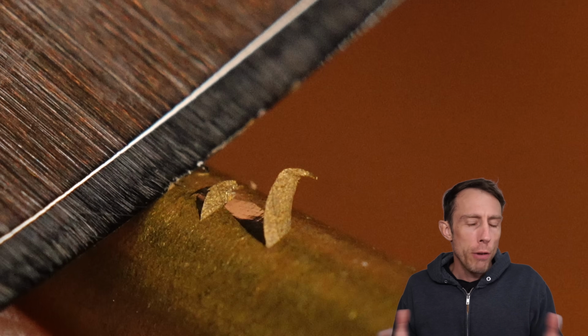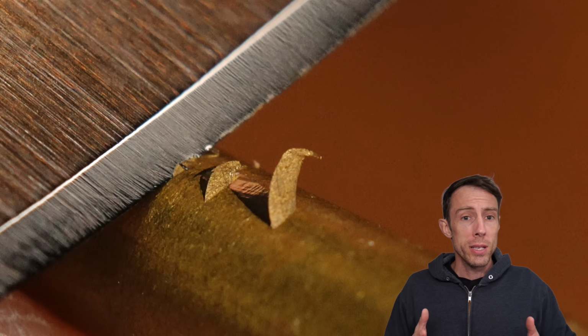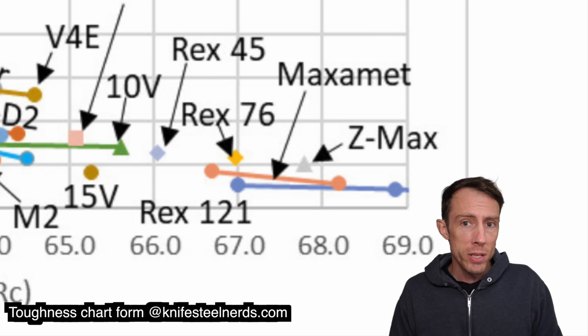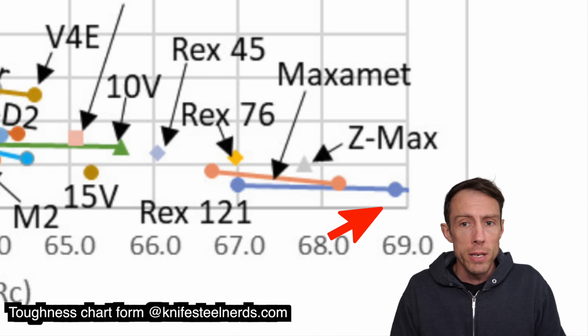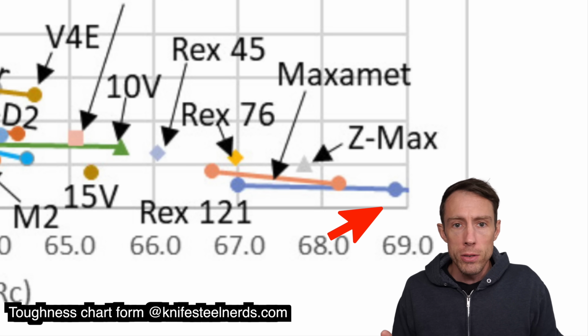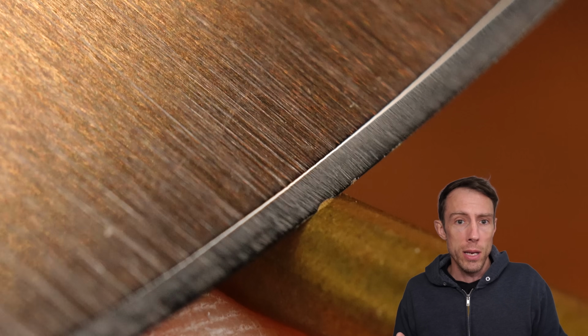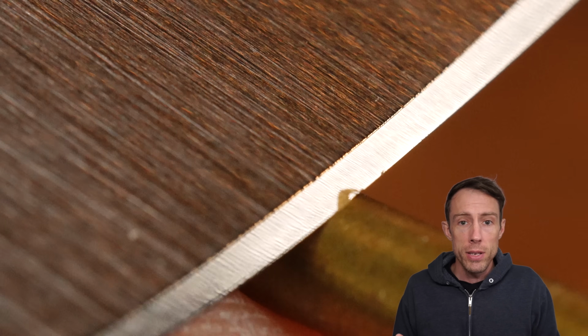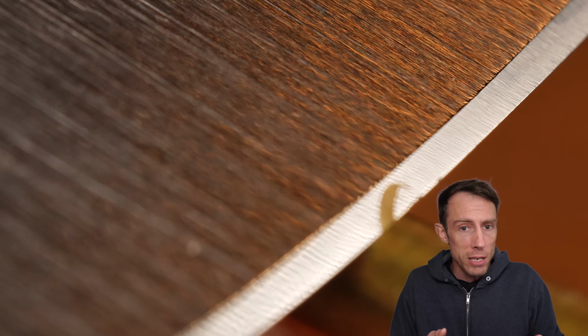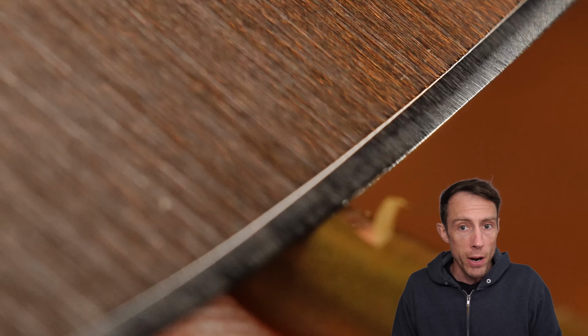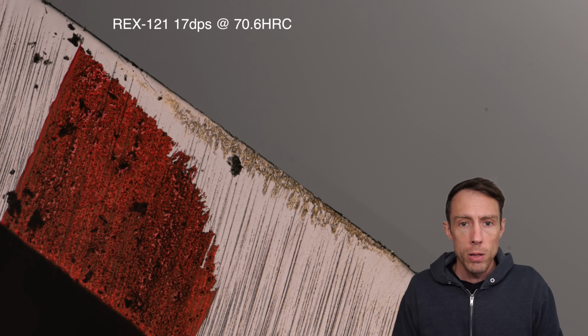So real quick, just how fragile is this steel? Well, I wanted to put this into perspective. While Rex 121 does have extremely low toughness, the steel isn't going to shatter into a million pieces the second that you do anything with it. To demonstrate just how resilient this edge can be, we can actually carve a brass rod at 17 degrees per side with very minimal to no damage along the apex.